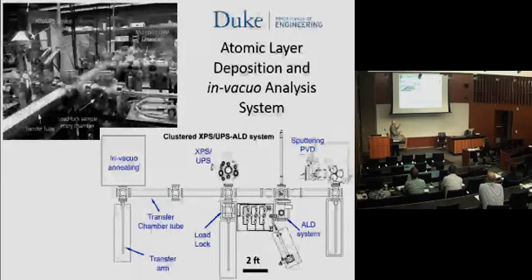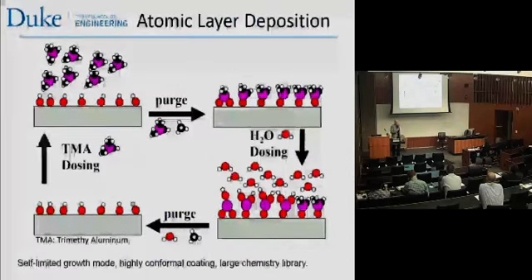If you don't have it connected in ultra-high vacuum and you take the sample out into the atmosphere, it's a different sample. So you can't think about understanding what's happening at the atomic level, layer by layer, as you develop these materials, unless you have an ultra-high vacuum transfer chamber. Also, we have a sputtering system and annealing to allow us to make changes to those materials that we grow in ALD, and to understand those changes layer by layer through the surface analytical techniques.